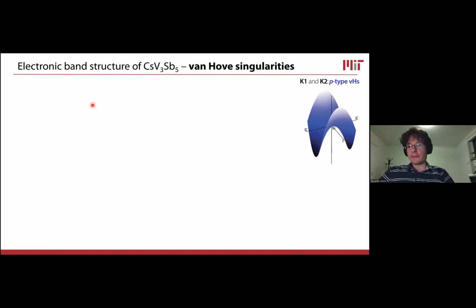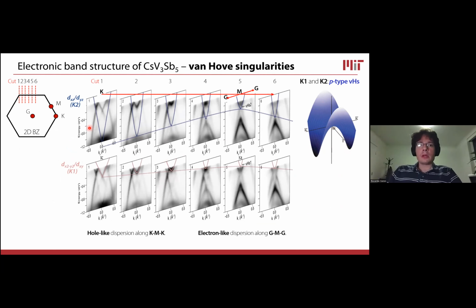So we can see these very clearly with photoemission. What we expect when we look at band structure data are dispersions where we have essentially a band that has a bottom. In the case of the p-type Van Hove singularity, we have a band that has a bottom and then a Dirac point at K, and the bottom of that band disperses upwards towards M. At the M point, you have the saddle point, and then the band continues down. And this is exactly what we see for the K2 and the K1 band. So for two of these Kagome bands, the pink and the blue that I was showing you in the previous schematic, we see that they have this Dirac point that's below the Fermi energy, and then the bottom of these bands, as we move from K to M, so we crawl along the edge of the Brillouin zone, goes up, up, up, and then reaches a maximum at the Van Hove singularity point, and then goes back down.